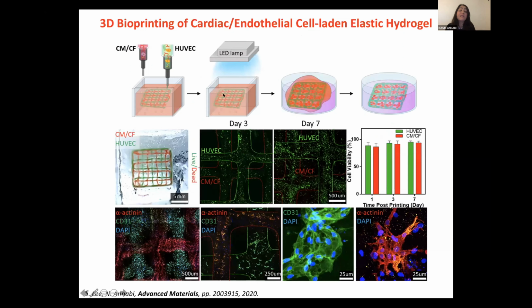And then as we form this multi-layer structure in the liquid bath, after we form it, we remove it from the bath and we place it in culture. And here in these images, we show that the different cell lines incorporated in different layers are all viable. We observe high cell viability, and also the cells express the right proteins. For cardiomyocytes, we did a staining for sarcomeric alpha-actinin, so the cells express this protein. And for the endothelial cells, we did a staining for CD31.